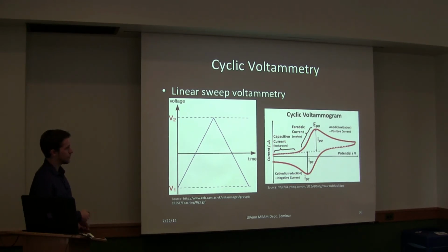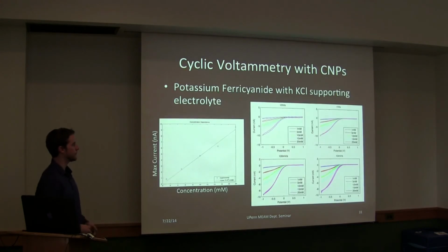And then you eventually hit a point where it becomes diffusion limited, so the peak dies off even though you're increasing potential. And then as you scan back the other way, you get the cathodic reduction current due to the reduction of the Faradaic species. And based on the location and the magnitude of these peaks, you can tell various things about the kinetics and the nature of your system.